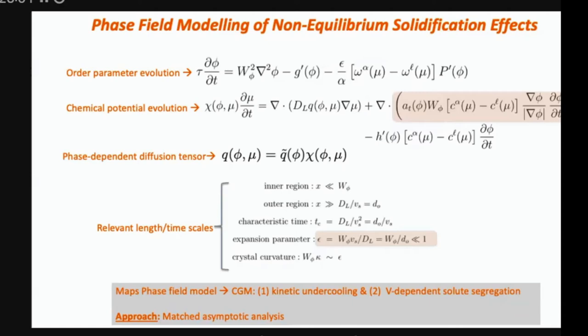And if you just naively do dimensional analysis, you get three length scales, the length scale of the interface, the length scale of the curvature that's possible based on surface tension, and a length scale based on thermal transport. These three length scales are always used, but their combination to create a scaling function is still not universal.